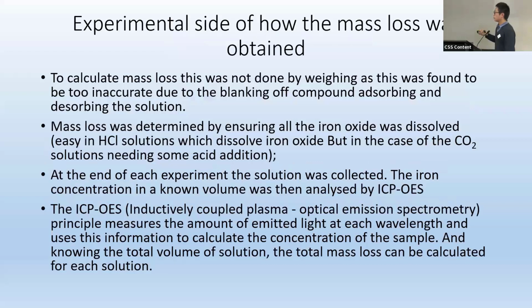Before I show you some results of this work, I would like to mention the mass loss. To calculate mass loss, I didn't use the traditional way of weighing the specimen before and after the experiment, because it is inaccurate. The coating compound can gain and lose weight by absorbing and desorbing the solution. So this mass loss work was done by the ICP test, which can calculate the ion concentration dissolved in the solution.